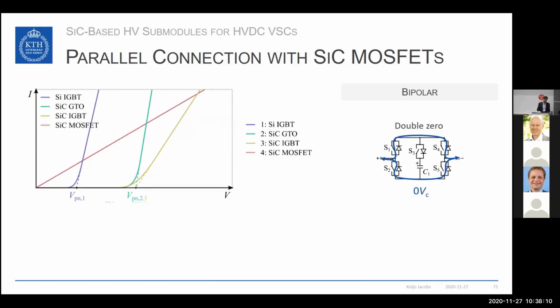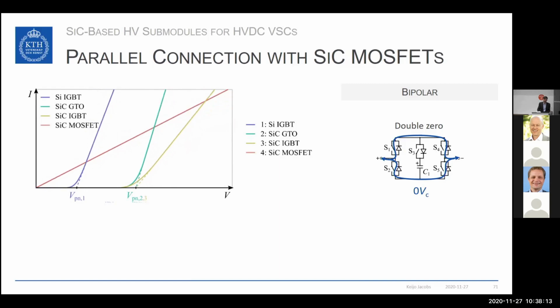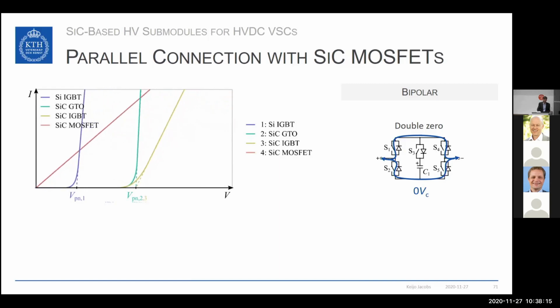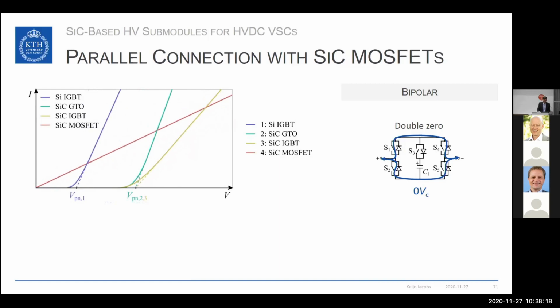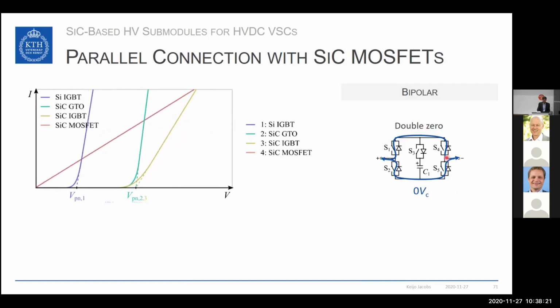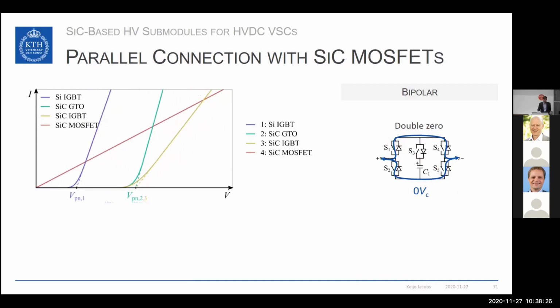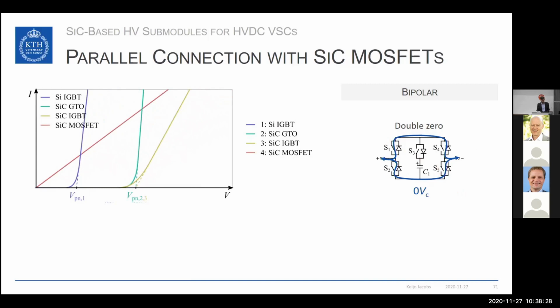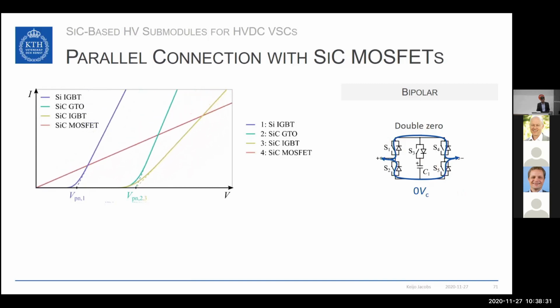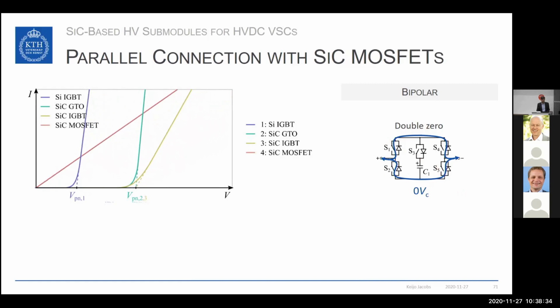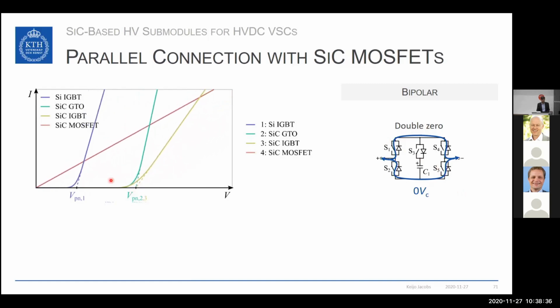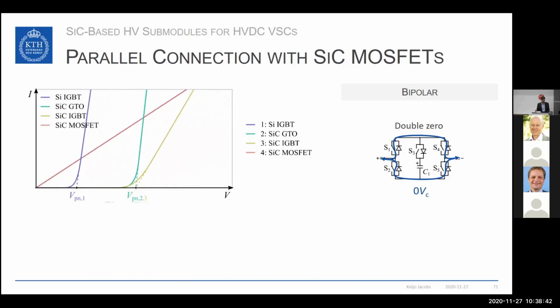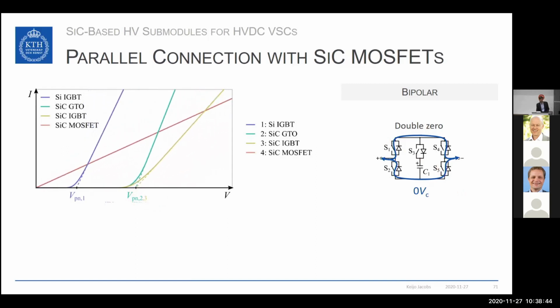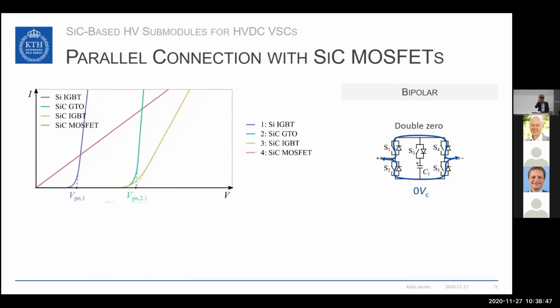If we now parallel connect these devices, either in a power device by connecting several of the dies in parallel, or in a submodule by parallel connecting different current paths, then we can decrease the resistive part of these devices. And this is indicated here in this GIF. As you can see, the loss reduction in the bipolar devices is limited by the built-in potential. However, the silicon carbide MOSFET doesn't have this limitation, and therefore we can theoretically get an arbitrary reduction of the conduction losses. And of course, you have to pay this with silicon carbide area.